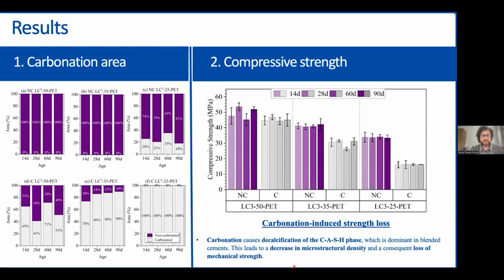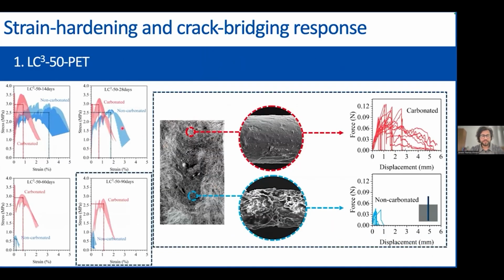Now let's take a look at the tensile properties. So I will start off with LC3-50 composites. What we will look at is the strain hardening behavior and the crack bridging response of these composites. Here, you can see the stress strain curves at different ages: 14 days, 28 days, 60, and 90 days. The blue envelope shows the samples that were hydrated, and the red envelope shows the samples that were carbonated before this prolonged hydration in the fog chamber. I also drew guidelines to mark where the average tensile strength and the tensile ductility of different composites lie.